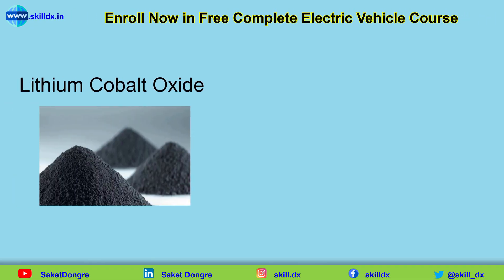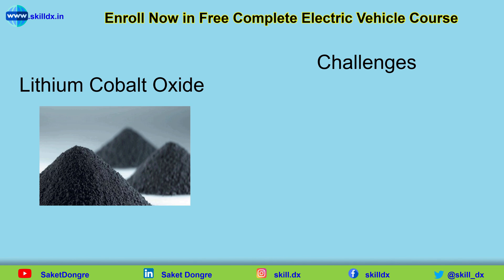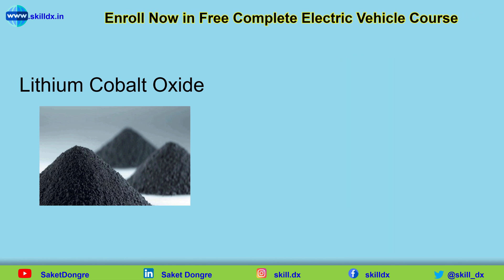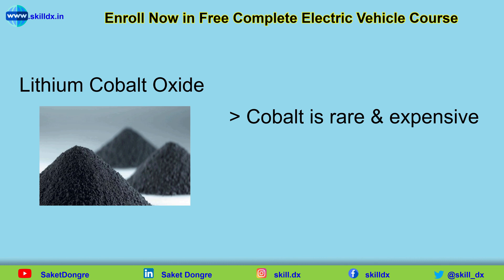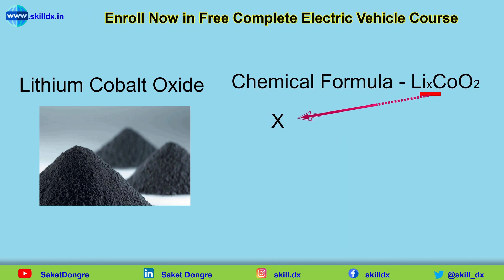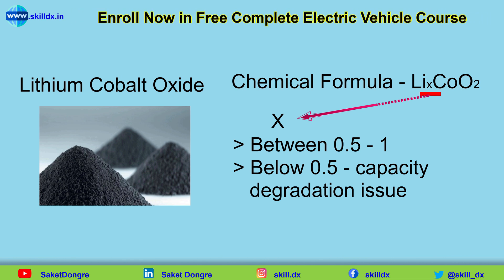Lithium cobalt oxide makes quite a good positive electrode material and is in very common use — found in portable electronics, laptops, and mobile phones. However, there are challenges when scaling up for very large applications such as vehicles or utility-grade use. Cobalt is very rare and therefore expensive, and it is also a toxic element. Another challenge is that we can only use about half of its theoretical capacity — the value of X can only go between 0.5 and 1, because going below 0.5 causes capacity degradation issues.